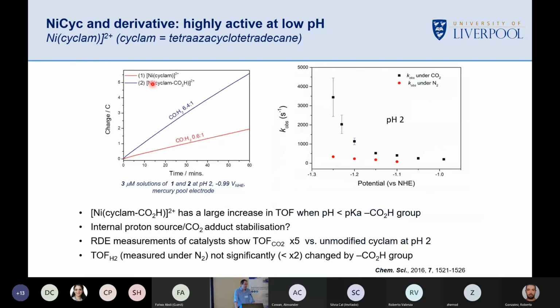It's not as selective. It's just under 1:1. Here's the observed rate on a rotating disk electrode experiment for our modified cyclam. You can see it's got quite high turnover frequencies. It doesn't show this large acceleration that the normal cyclam does. Sorry, the modified cyclam does. But it's still in itself a very good CO2 reduction catalyst, and it's incredibly easy to make as well.